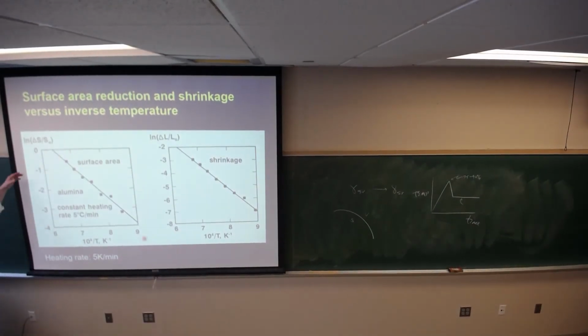This is normalized. I'm not sure why they're using the natural log. We still debate on that. It's delta S over S0, and then this is 1 over temperature on the x-axis, basically. And we're looking at what that reduction in surface area is. We took this data and converted it to other data we're looking at, and they match. It's quite interesting. He didn't do it quite with his natural log of delta S over S.